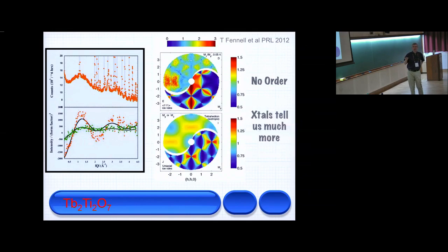We all have to start somewhere, and this was great as a powder experiment, but now with single crystals, you see there's much more detail. If you probe it in different directions, you get much more. You can then model it, which is these more colorful plots. So this is the data, and this is the plot in different types of scattering. You can try and model that. And you see, this is the best we can do today.